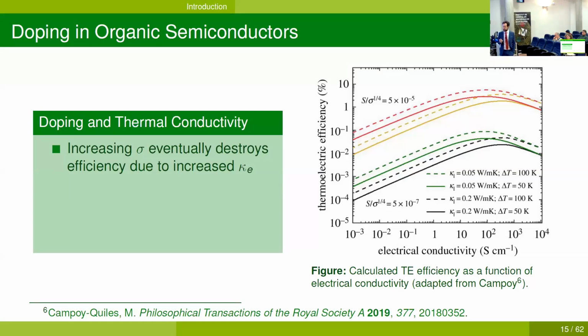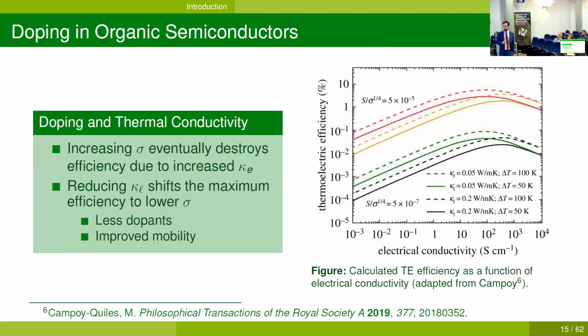So increasing sigma will eventually destroy the thermoelectric efficiency due to this increase in the electronic component of kappa. Yes, which we can see in the graph. Actually, there's a maximum. When we increase the electrical conductivity too much, the thermoelectric efficiency starts going down. And the other thing to note is that reducing the lattice component of kappa shifts the maximum efficiency to lower electrical conductivity.